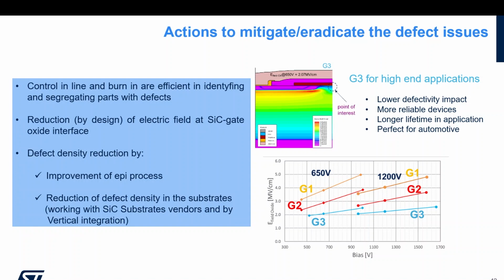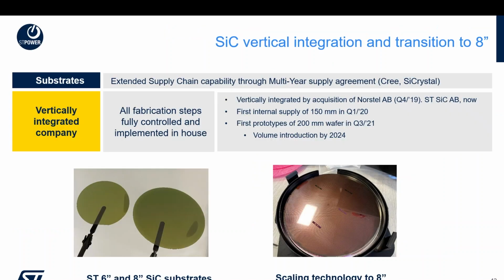The other thing that you can do is, of course, getting vertically integrated, which is something that we did in 2019 through the acquisition of Norstel, which is now ST SiC AB. So that we are also able to produce our material internally at 6-inch and 8-inch. And you understand that more than being just connected to the availability of the wafer or the cost of the wafer, it's also linked to the fact that this is going to control the performance of your device. While in silicon you have a standard substrate or substrate plus epi that you can buy from outside that comes without defects, this is not true for silicon carbide. This is one of the main differences today in the manufacturing flow.